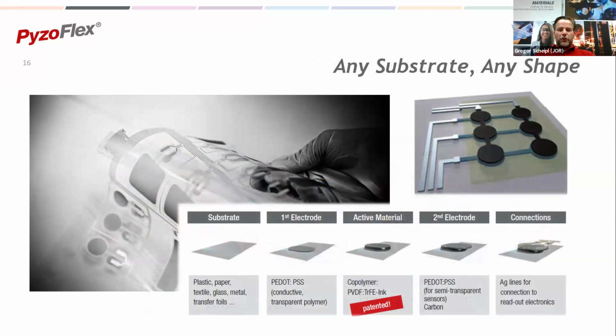So the sensor, or the core of the technology basically, is, of course, the printed device. I think most of you will be familiar with printing. It's screen printing, and we have various substrates like PET foils, paper, Kapton, polypropylene. I think nearly any given substrate, as we can print a primer to make it ready for printing the sensor following. And it's then the first electrode, it's like a vertical layer stack-up.